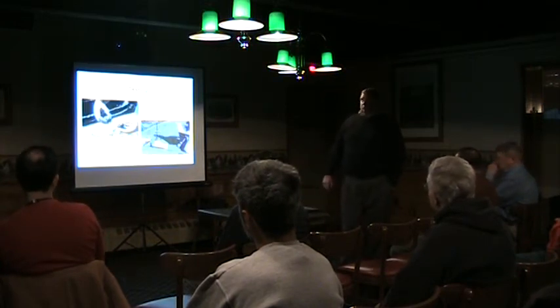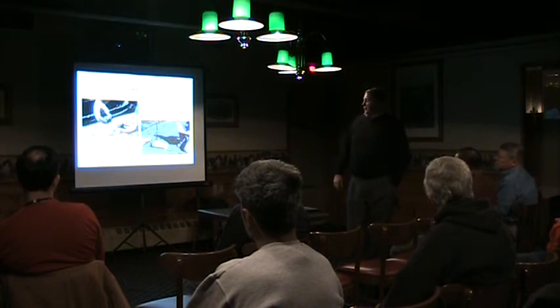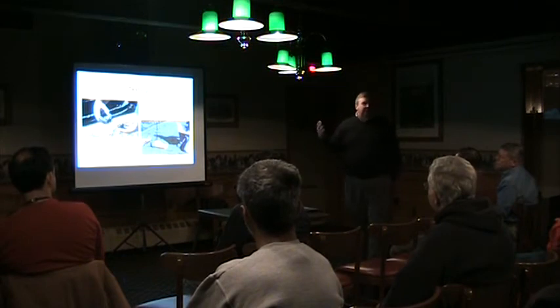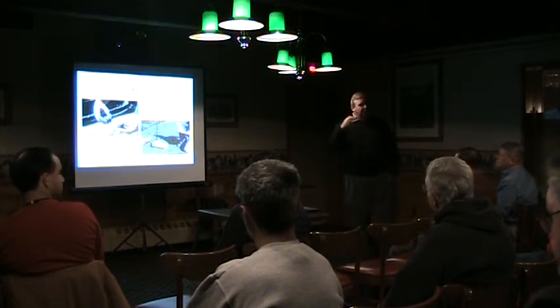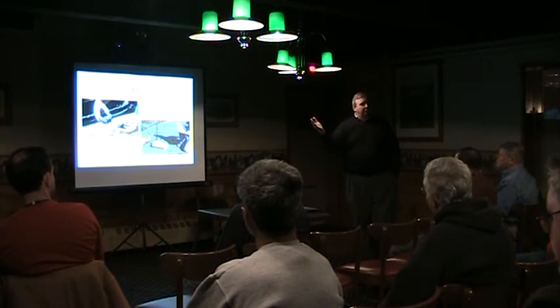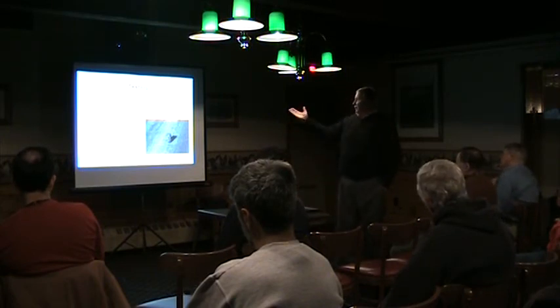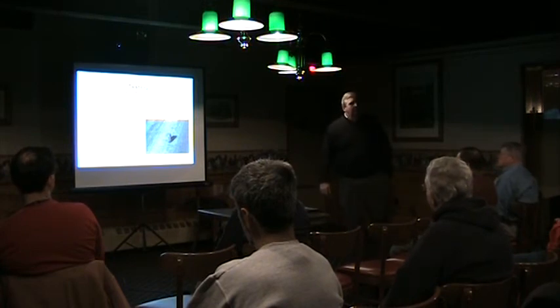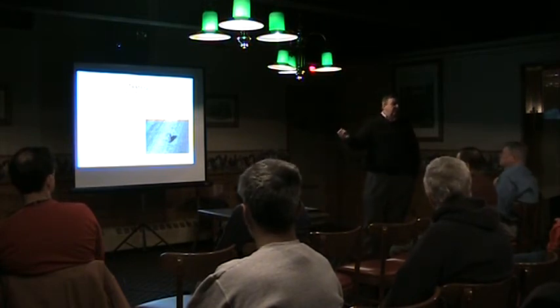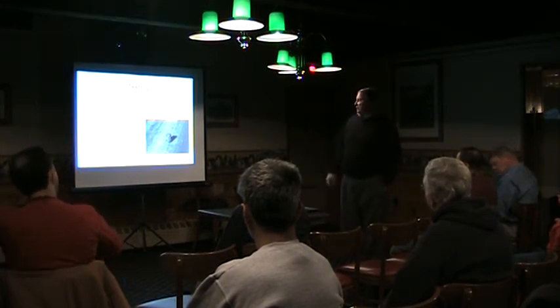Testing. We're going to do moisture tests in the field, and also densities. And as far as the frequency of testing, that's really going to depend on what we specify up front. As long as the contractor knows going in what he has to do, there's typically never any issues. In this particular presentation, we're talking about 100 feet each lane. That's a little excessive. Once you get those densities down with the cement, you know you have the right dosage rate of cement, the density is going to remain relatively the same all the way through.